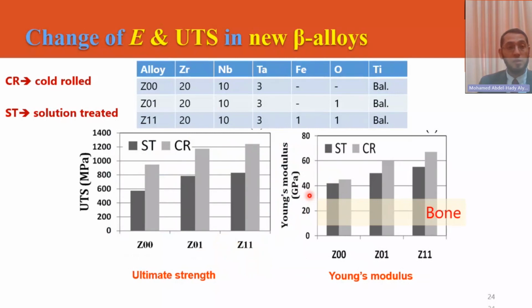Actually, alhamdulillah, we did some work on this, and we can see some of the alloys that we have developed based on these theories: titanium, zirconium, niobium, tantalum, with some minor modification with iron and oxygen. We can achieve very low Young's modulus, very close to that of bone. The bone is in this range, okay? And we can achieve this. So how can we do it? By composition, as I said, and processing: cold rolling followed by solution treatment. So these conditions are material processing combined with composition, so we can achieve the required properties. And this is the strength of these alloys, which is acceptable compared to the commercial alloys and so on.